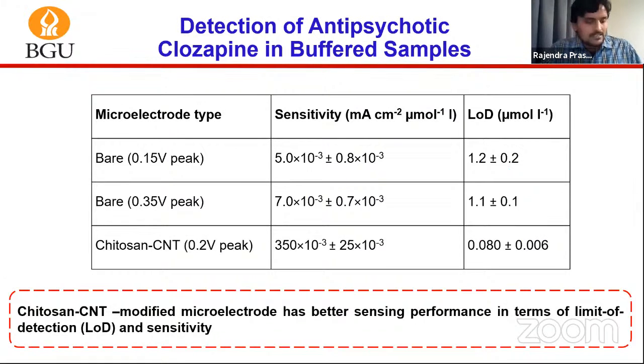From there, we plotted a dose response plot and calculated the limit of detection and sensitivity. For the bare, you can see the limit of detection is 1.21, and for the chitosan carbon nanotube modified microelectrode, the limit of detection is 0.08. So it is almost 10 times lower, and the sensitivity is also very high as compared to the bare microelectrode, meaning that our chitosan carbon nanotube modified microelectrode has a better sensing performance as compared to the bare.